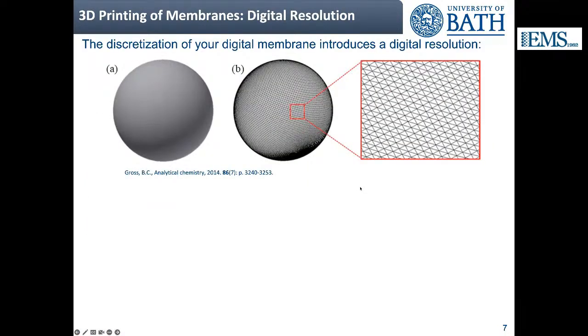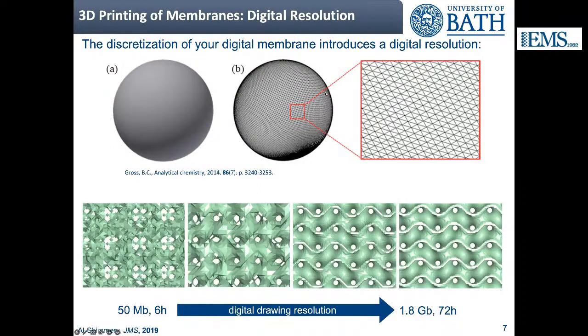The second point is digital resolution. When you're discretizing, say, a pore, or in this case a sphere, that will be discretized as many triangles. And of course, the more triangles you have, the closer you get to a perfect sphere or a perfect pore, but nonetheless, it will never be an ideal circle or sphere. An example you see here, going from left to right, is the exact same porous structure in CAD, but as we go from left to right, we increase the resolution, and you can see that in the rightmost image, you have very well-defined pores and this tortuosity, which I'll talk about later.